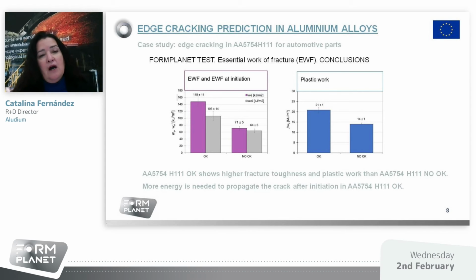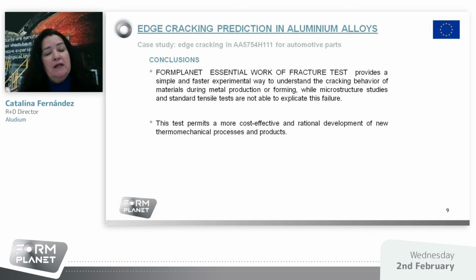And finally, our conclusion regarding the FormPlanet test used in this case study is that the essential work of fracture test provides a simple, faster experimental way to understand the cracking behavior of material during metal production or forming, while microstructure studies and standard tensile tests are not able to explicate this data. Also, these tests permit a more cost-effective and rational development of new thermomechanical processes and products in aluminum alloys.